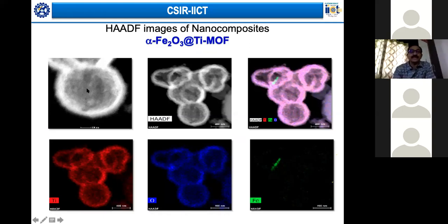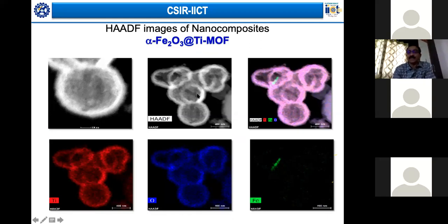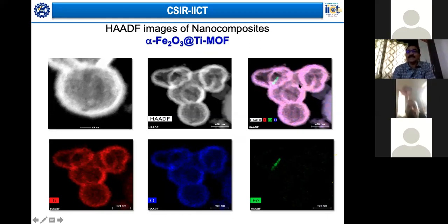So if you see, this is the TEM image, and this is a HAADF image. Here you can see an image of the overlay of all the elements present in the material. And here you can see that most of it is titanium. That is why all this shape is of titanium and oxygen, whereas the small area here is due to the iron that is present. So by this chemical mapping, we are able to locate the materials and their distribution in these kinds of materials.